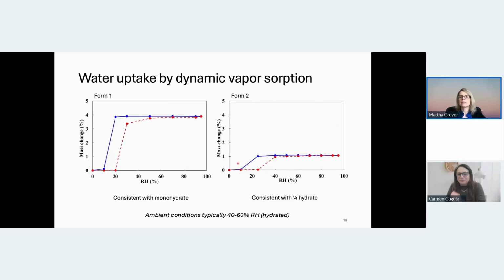So let's just go back to the DVS. So we do have water that is being taken up. I also should point out here that ambient conditions, we typically associate that in a controlled internal environment with 40 to 60%. And so that would be on this side where we would have water uptake. We don't always record the ambient humidity, so we don't know for every measurement, but the XRD is done at ambient conditions. So when we start, we would be on the hydrated side.